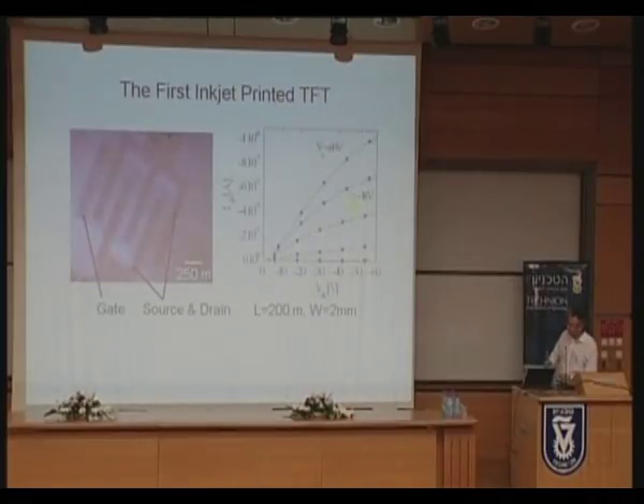Now, I have to say, the first transistors we made were pretty hopeless. That m should be a micron. They're huge. That's a quarter of a millimeter, that space bar. The problem is that drops out of inkjet printers are actually relatively large. They may be quite good for home photography, but compared with Pentiums, they're not much good at all. A drop size is about 20 microns, about the width of a human hair.